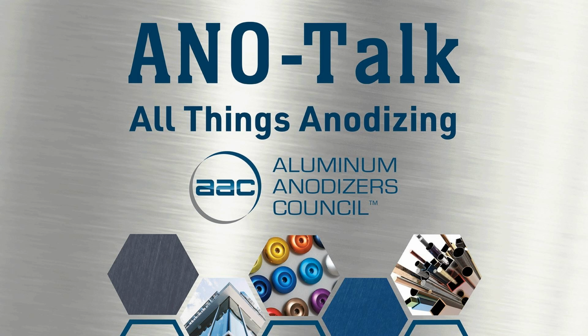In anodizing, we are changing the structure of the oxide layer depending on what we are pushing through the system. So you can actually play around. It could be when you, for example, do pulse anodizing with type 2 and you want to dye it with organic dye, so only in the top layer. So you want to have the layers, maybe only the top or the last part of the process, at a different current density compared to the beginning. So you can actually start playing around.